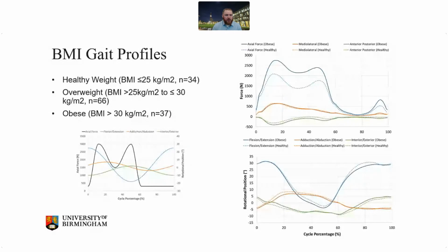Compared to the ISO profile, we split the patient demographics into healthy weight, overweight, and obese patients, and we ran a hip simulator test, which I'll get to the data in a second. We ran a hip sim test in order to compare these two different profiles. You can see, compared to the ISO walking profile with the standard twin peak, and then basically a set of sine waves for the rotation axes, the loads are very different. Loads are lower, typically for a start, even for the obese patient, than the 3 kilonewton peak called for on the ISO profile, and the kinematics are very different.